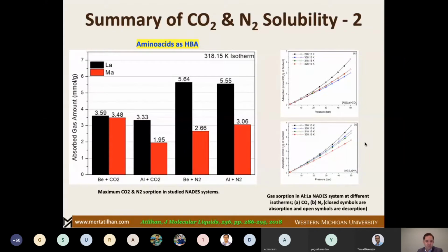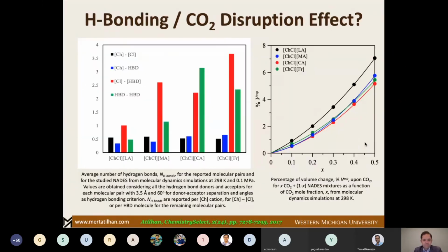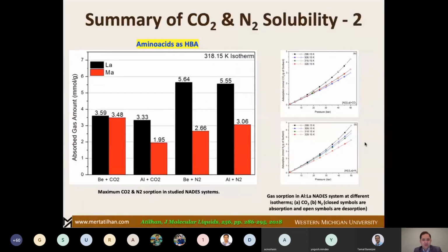DES and NADES did not really show us this sort of behavior. It was very smooth absorption, desorption, no hysteresis, no chemisorption that we observed. Which means that whatever we started at the 0 point, we increase the pressure, then when we come back to the vacuum point, which means we release the pressure, we were able to regenerate the system completely. I think I forgot to include a slide here that shows the repeatability.